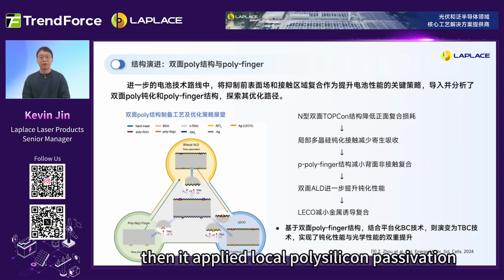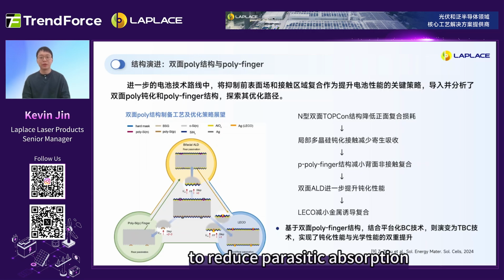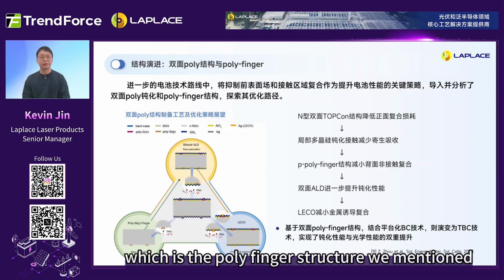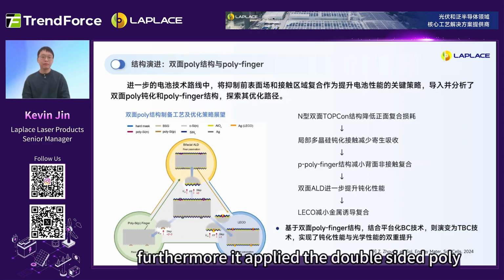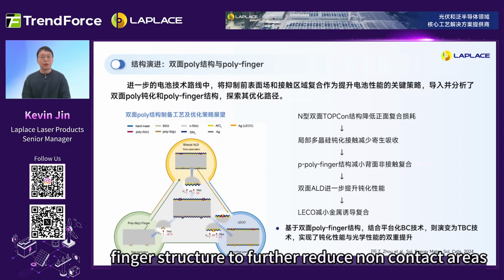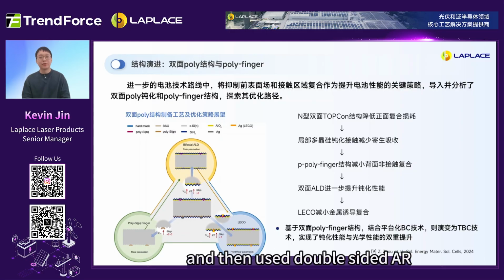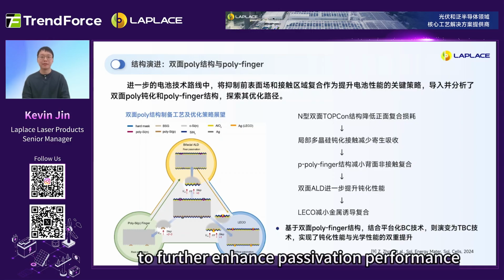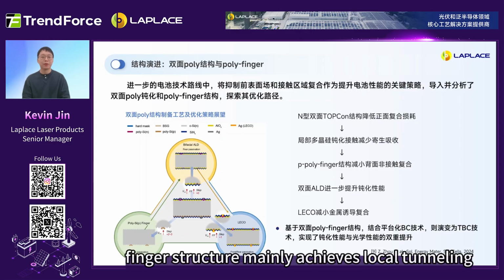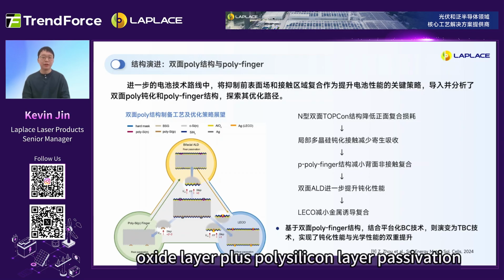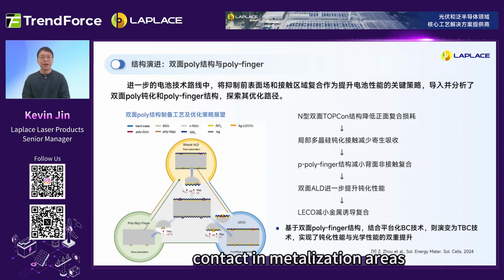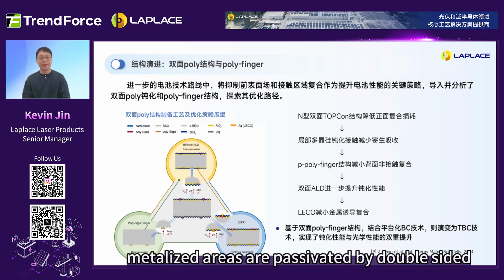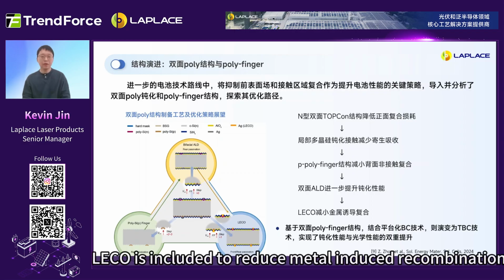Then, it applied local polysilicon passivation to reduce parasitic absorption, which is the polyfinger structure we mentioned. Furthermore, it applied the double-sided polyfinger structure to further reduce non-contact areas, and then used double-sided AR, anti-reflective coating, to further enhance passivation performance. The polyfinger structure mainly achieves local tunneling oxide layer plus polysilicon layer passivation contact in metallization areas, while non-metallized areas are passivated by double-sided aluminum oxide. Finally, LECO is included to reduce metal-induced recombination.